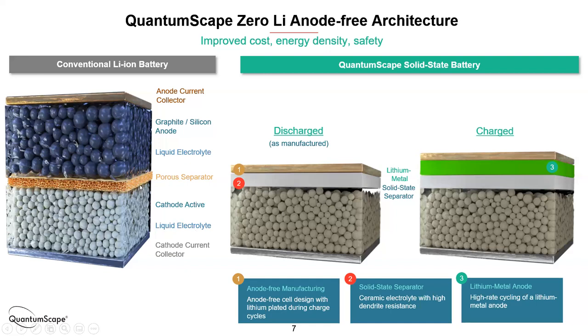But on top of it, instead of that porous separator and a hosted anode structure, we just have a single sheet of solid electrolyte. So it's a fully dense solid that is impenetrable by any liquids or gases for that matter. On top, all we need is a current collector. So in this case, as you can see, there's basically no anode at all. It's a pretty interesting structure. So to form the anode, we actually have to charge the cell up. So we build the cell and we do its very first charge, and in situ, this green, fully dense metallic lithium layer forms. Because we don't have the host structure, all those racks for storage of lithium ions, it ends up being significantly more dense than the conventional lithium ion system.